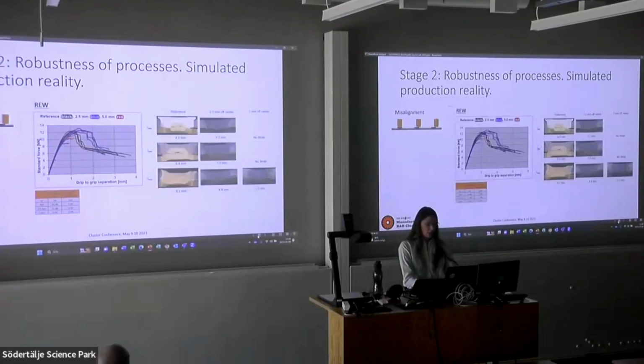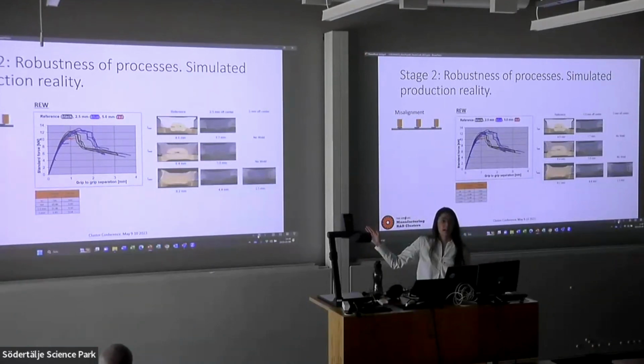But then, of course, for resistance element welding, there is always the problem that you do not hit your resistance element in the center itself. You might miss it somewhat. So we tried missing 2.5 millimeters or 5 millimeters. And here we do see a clear impact both in shear tensile strength and in weld nugget size.